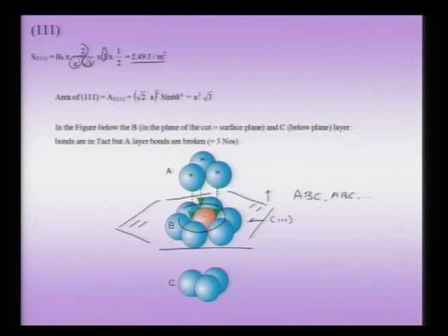So, this is my least energy surface in copper, and this is not surprising because we know this is the surface which shows the close packed planes. These are the closest packed, highest density planes, and therefore, I expect this to be the lowest energy. So, using the example, we have tried to calculate, in a very simplistic way, the surface energy of various kinds of planes in copper. Of course, I could consider even higher index planes and try to calculate their energies, but at least for comparison we have 3 rather low index planes, and therefore, we can find which is the lowest energy of these 3.